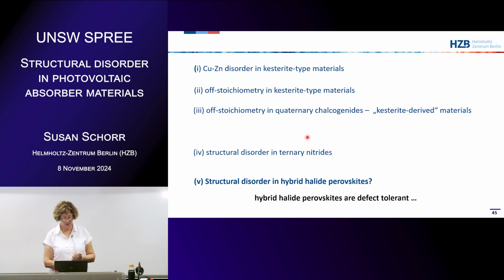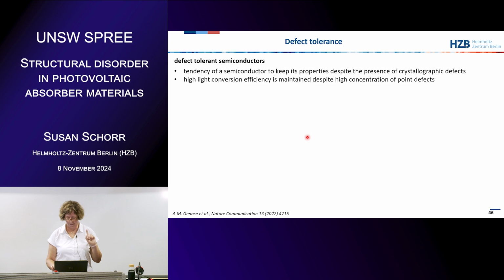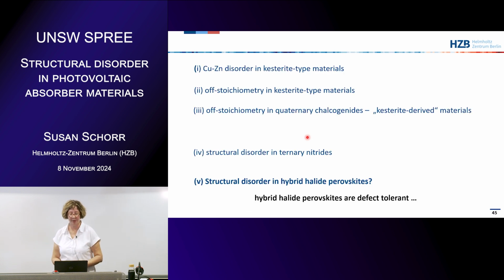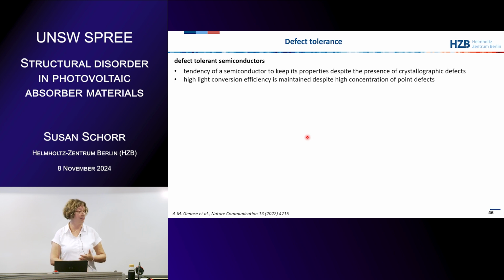So the last point I want to touch is the hybrid halide perovskite, just quickly. The question was, is there structural disorder in hybrid halide perovskites? Okay, hybrid halide perovskites are these amazing materials which are defect tolerant. But then people say, we can forget about structural disorder, defect tolerant material. So what does defect tolerance mean? Defect tolerance for a semiconductor means that the material keeps the properties despite the presence of defects. So this material still has in the solar cell the high conversion efficiency, even if it has a high concentration of point defects.